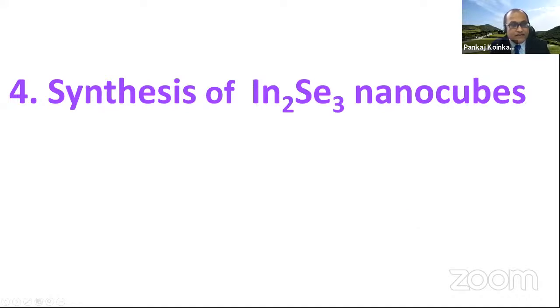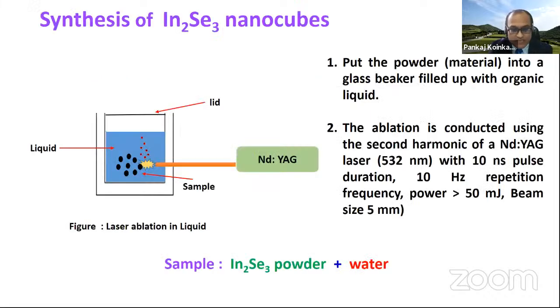And now I will explain the synthesis. We have synthesized indium selenide nanocubes using this process, where we used indium selenide powder as the bulk material, and we irradiated it using an Nd:YAG nanosecond laser with a wavelength of 532 nanometer and a pulse of 10 nanoseconds. The energy is 50 millijoule. The size of the beam is 5 mm. The laser beam size, I'm talking about the diameter of this laser, is 5 mm. And we irradiated for about 20 minutes.